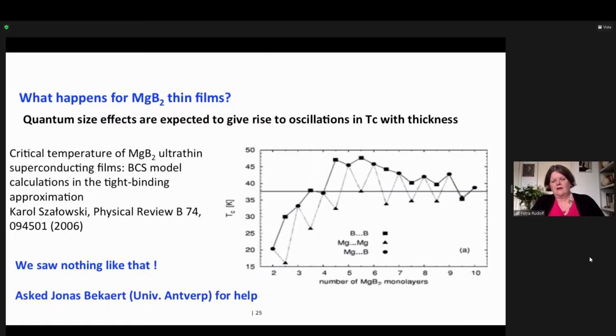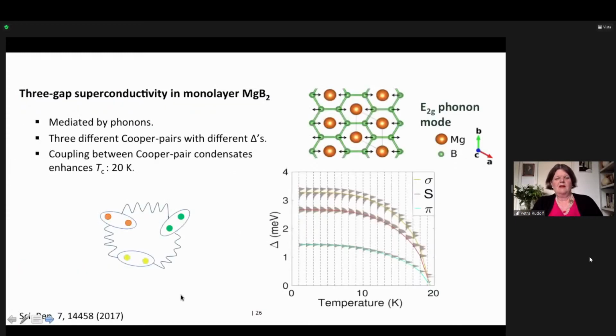So we went to the University of Antwerp because our friends there, and in particular Jonas Bekaert in the group of Francois Peeters, agreed to help us and to calculate. And what he did was to consider the monolayer first. And what he found is actually that the story is completely different. The predictions that had been made before never really considered surface electrons.